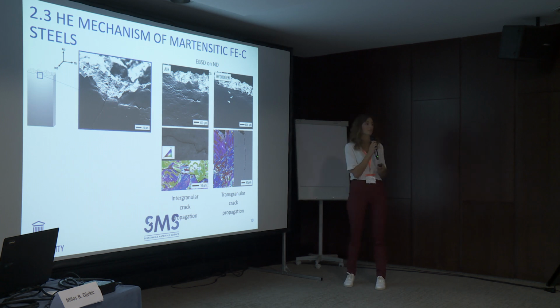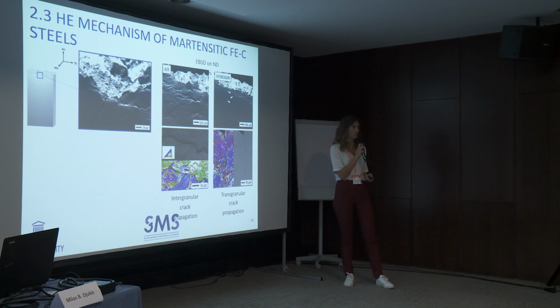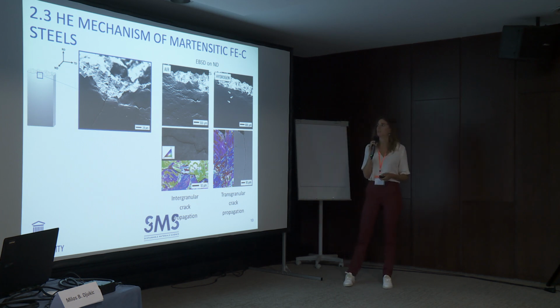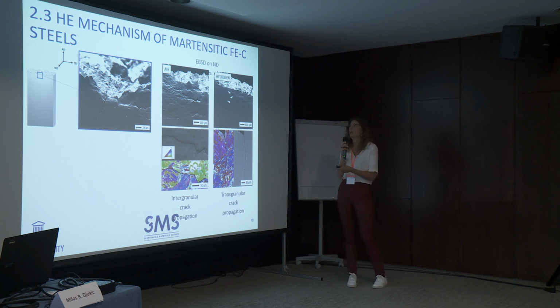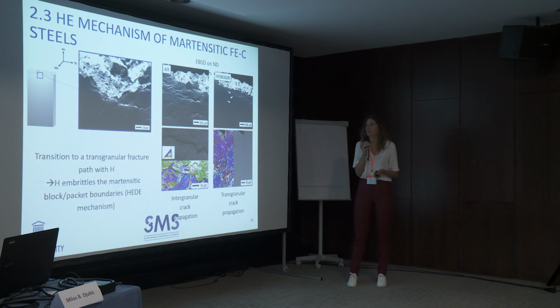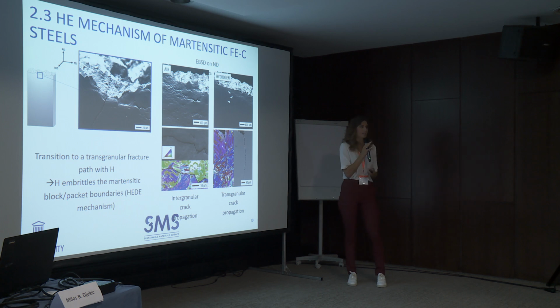To investigate this in more detail, I also looked at the cracks which are formed on the ND surface at the tensile side of this bending specimen. And what we see, this is an example for one material, but we saw this for all three materials, is that in air we have a mainly fracture propagation path along the parent grains. But when we charge it with hydrogen, there's a transition, and we see cracks appearing along the martensitic blocks and along the martensitic packets. So hydrogen, in fact, embrittles the martensitic packets and blocks.